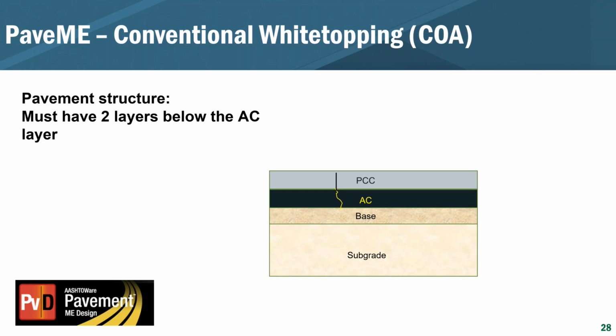Another thing with conventional white topping in your overlay design, so jointed plain concrete over asphalt, is that you must have 2 layers below your asphalt layer. And this can be important. A lot of agencies might be saying, well, we usually have a base and a sub-base layer or some type of select granular fill anyways, but in some of these thicker asphalt pavements, like they have throughout Iowa, these are full depth asphalt pavements that were constructed right on the subgrade. And so even though it's an asphalt directly on the subgrade, you will have to stick a base layer in there. And in the example, we'll talk a little bit on how that can be done.